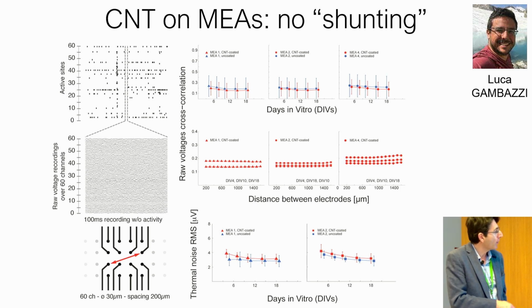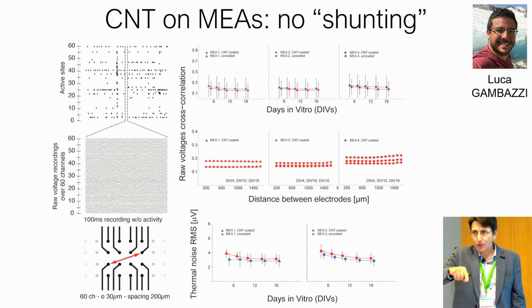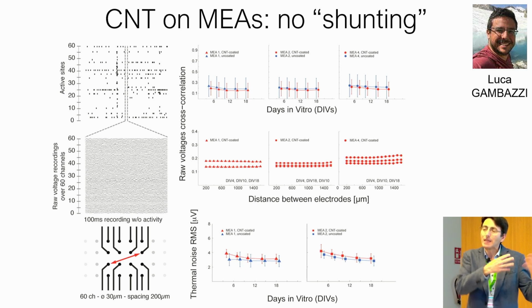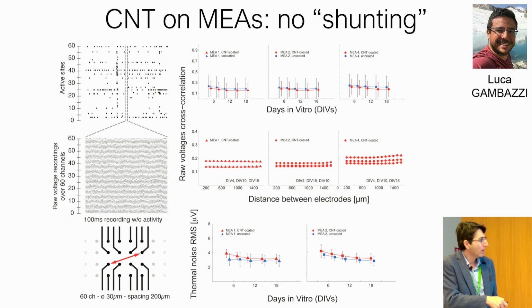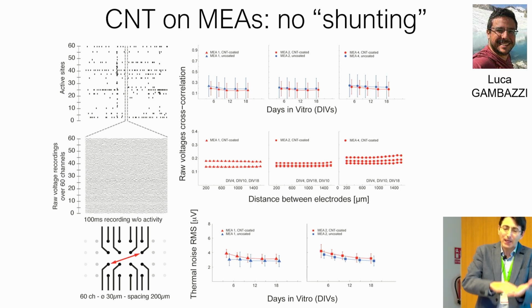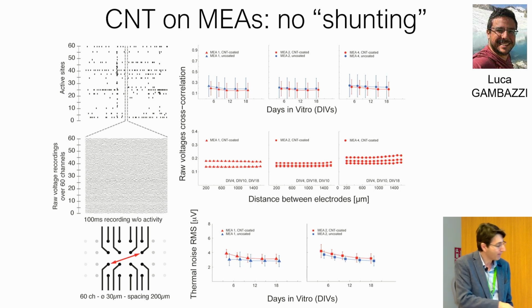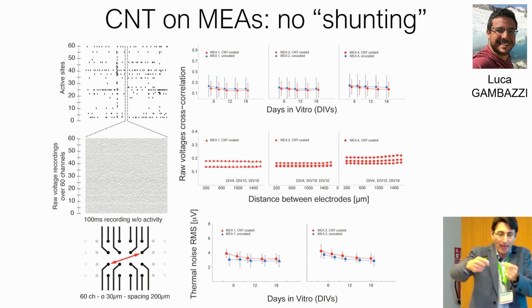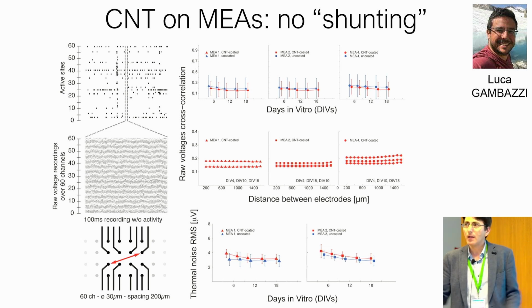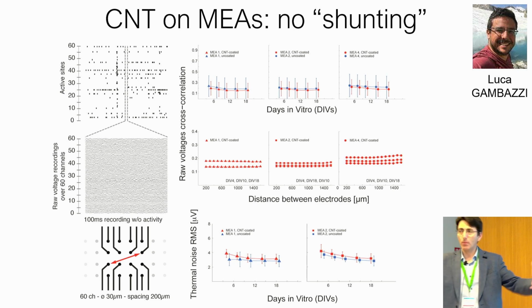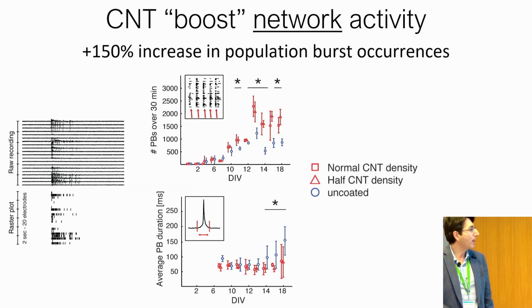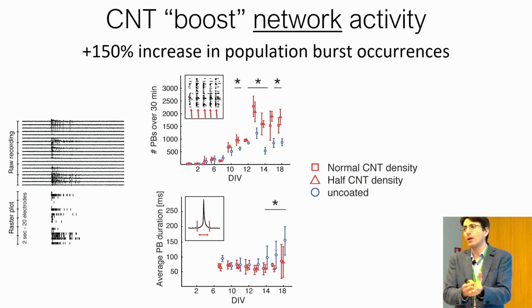And here what I'm showing is that even in the raw voltage, the noise that is related to the interface, there was no correlation. The correlation was not across days in vitro, was not different than the electrodes that were not coated. And this is probably due to the fact that despite you have this meshwork, the percolation length is relatively short. So yes, they are electrically conductive, but they don't shortcut electrodes that are 100 or 200 micrometers far apart.